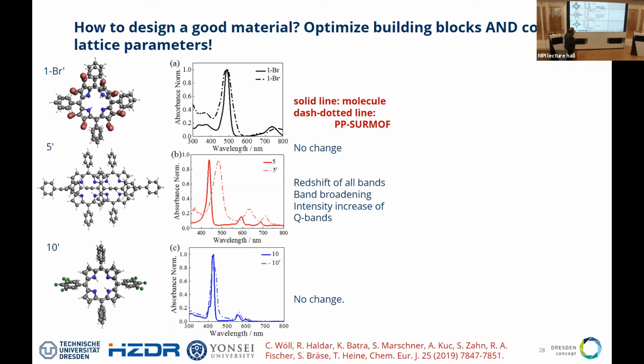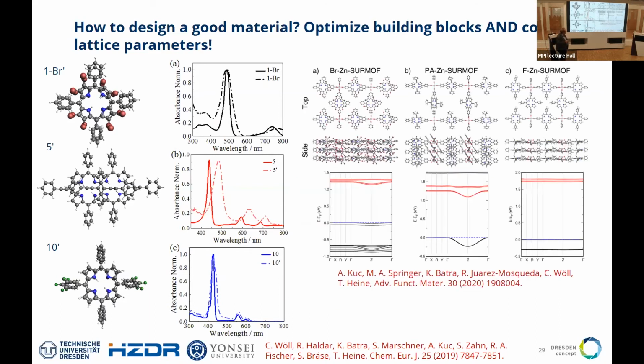And what you can see here in the solid line, that is the UV-vis spectrum, so the light absorption from the molecules, and the dashed dotted line is the light absorption of the solid. And you can see that the one in the center has a very strong response. The question is why? You do a band structure calculation, you realize why. Here and here, we have very poor band dispersion, but here we have a very strong band dispersion. If you look very closely, you see again that the direction along the stacking, right?